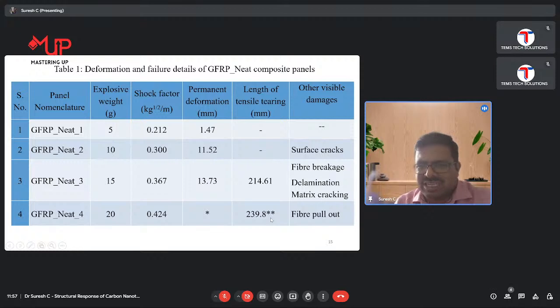This double star denotes that the structure is damaged more and it cannot withstand further loading. So the whole ship or submarine will get completely damaged. In 15 gram, we have seen the composite fiber breakage, and there was delamination and matrix cracking at the tearing edges. At 20 grams, the fiber is completely pulled out.